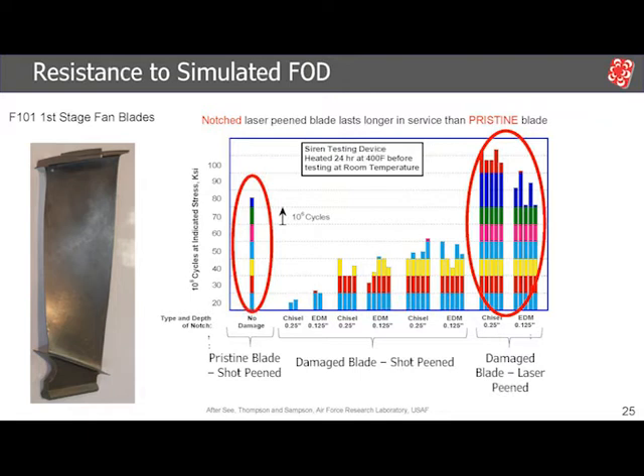And the problem here is foreign object damage, meaning something flies and hits the blade and creates a notch feature. You can see that the blade performance before notching is demonstrated here as a pristine blade. The minute that you have damage, you lose the majority of that life.